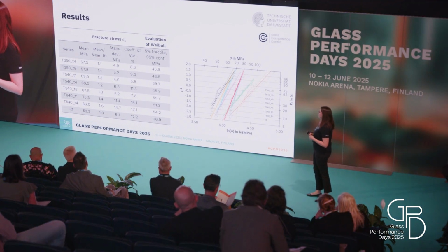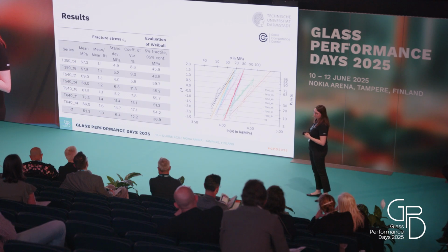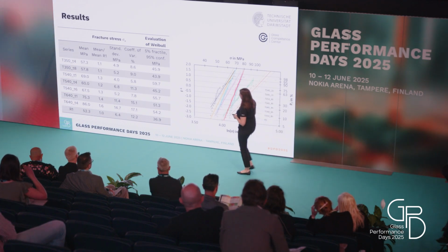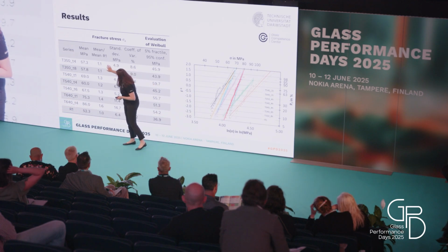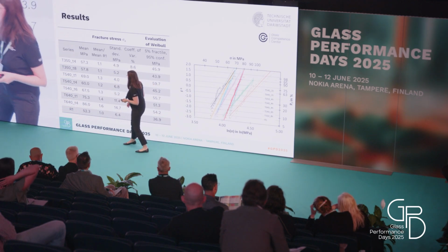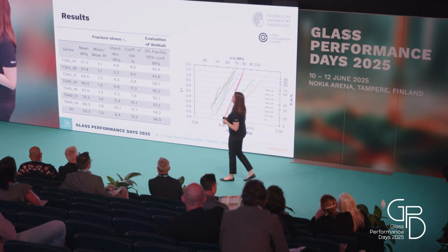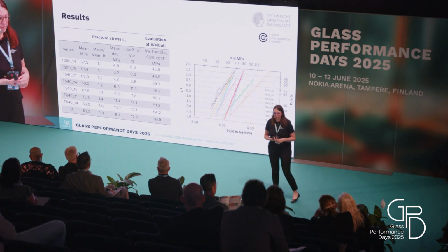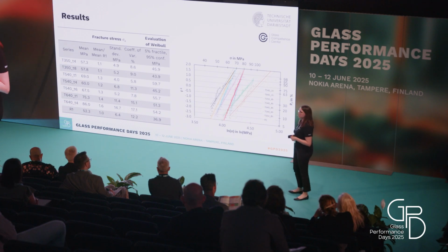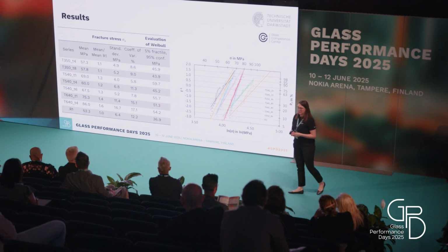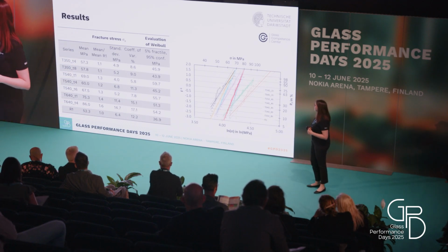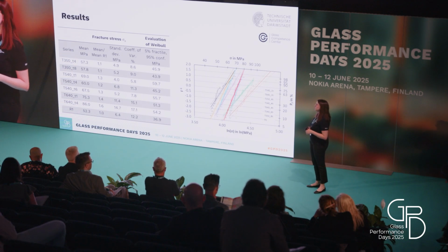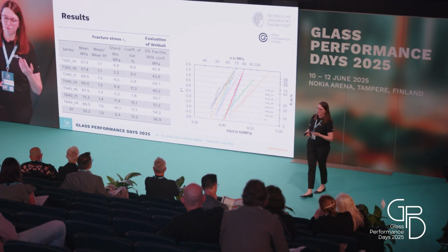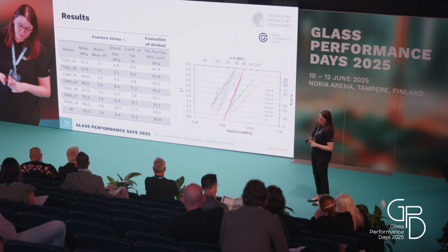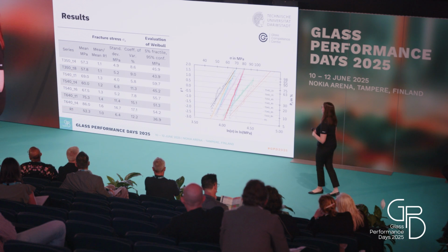So for the mean fracture stress compared to our mean fracture stress of the reference series, so the second column, we already see that we have an increase for the mean fracture stress for all the heat-treated series. Even at the low temperature of 350 degrees Celsius, we see an increase of 10%. It's low, but it's an increase. We also see that the higher the temperature, the more the mean fracture stress has increased. But we also see that the duration of the heat treatment does not really have a high influence, at least for the 350 degrees Celsius and also for the 540 degrees Celsius, we did not see a real influence.